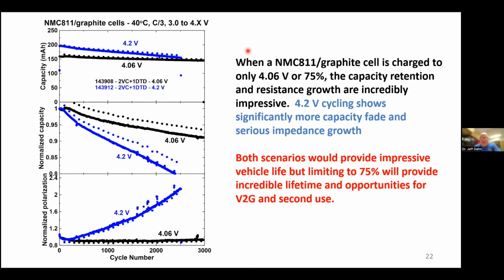Here's an example showing you the advantages of charging to 75%. So this is NMC 811 graphite cells. So typical lithium-ion cell operated at 40 degrees C with a 3-hour charge and a 3-hour discharge. Continuous cycling, 3,000 charge-discharge cycles. If you charge to 4.06 volts, which is 75%, you can see the capacity is less than if you charge to 100%, which is 4.2 volts for this cell. But you can see when you charge to 100%, the cell capacity degrades more rapidly than if you charge to 4.06 volts. And if you look at the normalized capacity, you can see after about 2,500 cycles, you're down to 80% when you charge to 100%. But after 3,000 cycles, you're still above 90% when you charge to 75%.